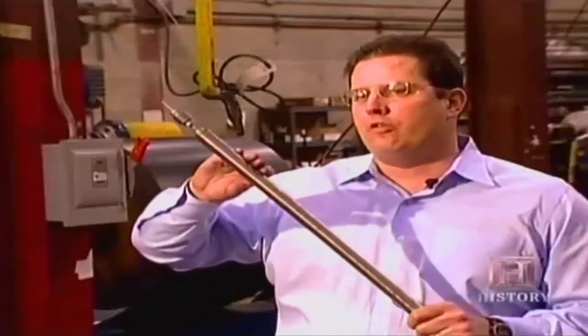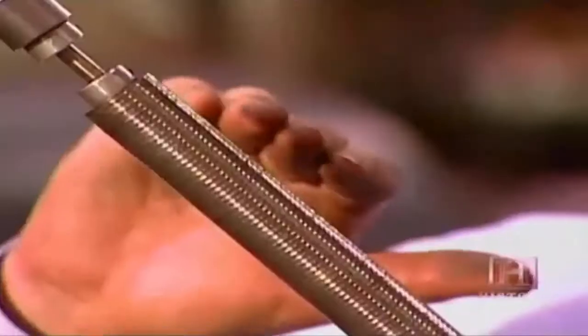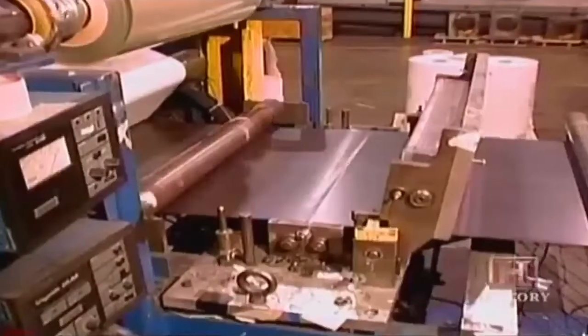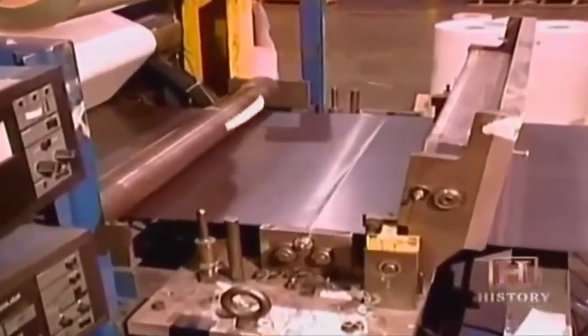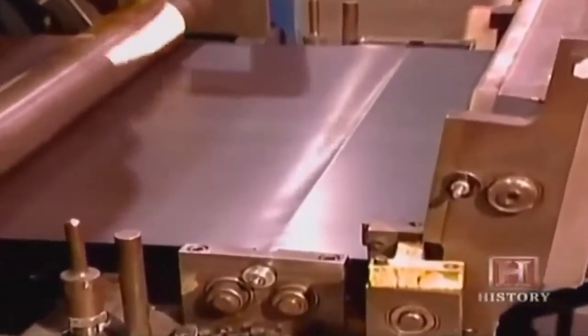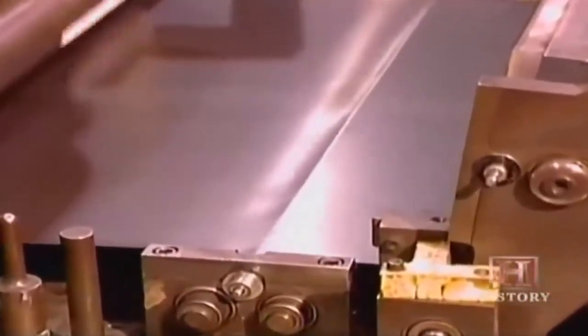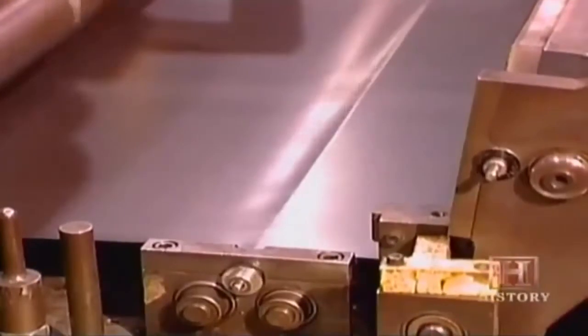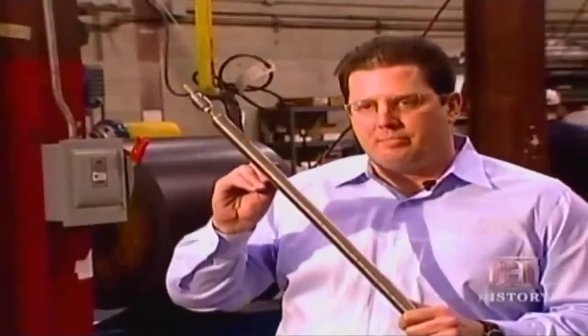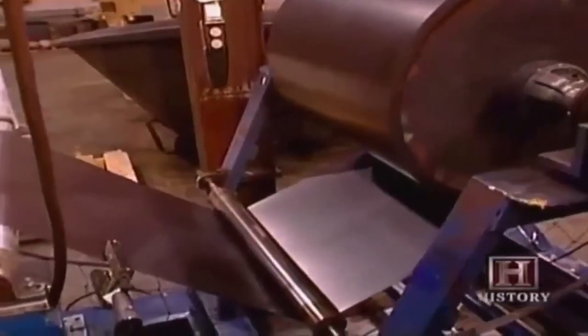Before the sheet passes over this roller, the small ferrite particles in there are really not aligned magnetically in any form or fashion. As they pass over this, the field that is produced off of this rare earth magnetic roller aligns those little particles in the sheet to create a magnetic pattern on the sheet. And those would be a mirror image of what this magnetic pattern is on this roller.